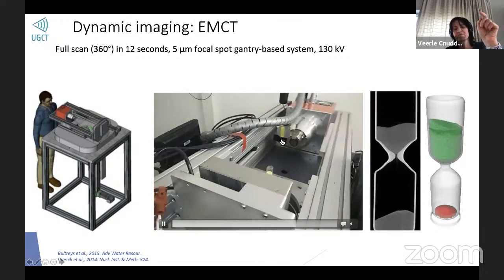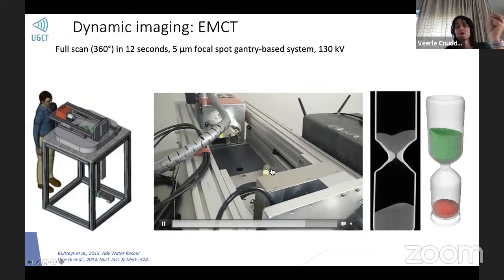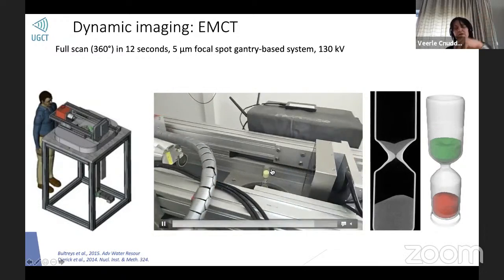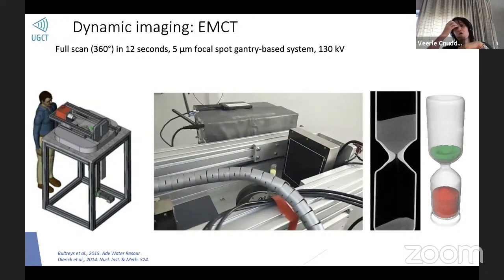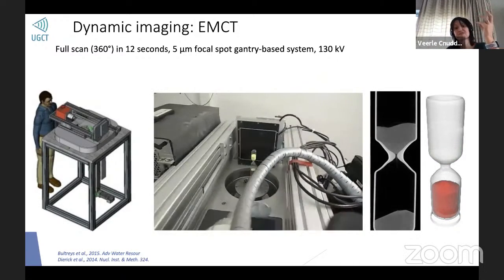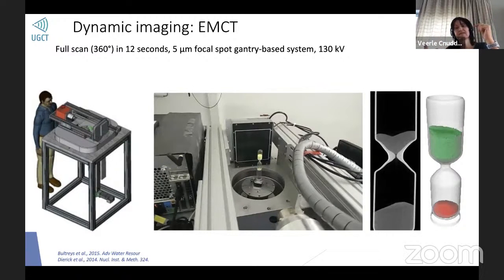But the thing is, if you want flow wires attached to your sample, or temperature sensors, having everything rotate for 20 minutes can also be a challenge. Sometimes with fast imaging, if you're working with liquids, we do not want our sample rotating very fast. So it's good that our source and detector are rotating instead. This is our environmental CT scanner.